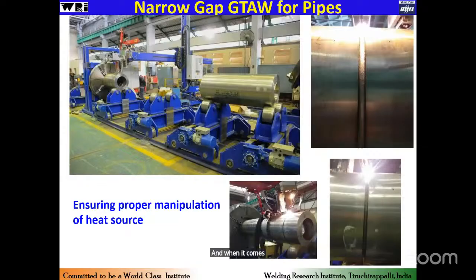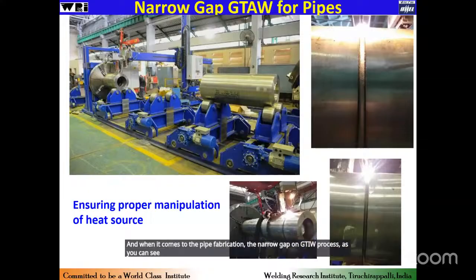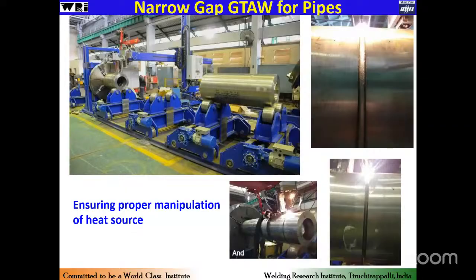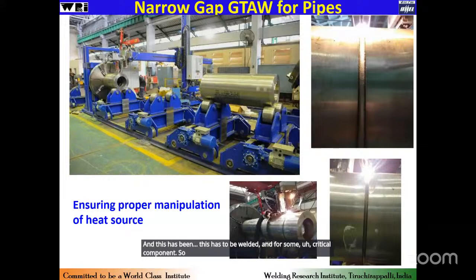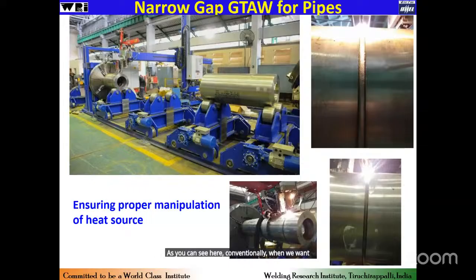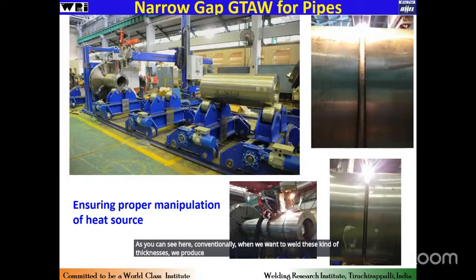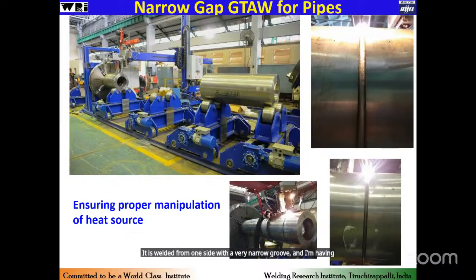And when it comes to pipe fabrication, the narrow gap hot wire GTAW process, as you can see here. Conventionally this grade of material is a nickel based superalloy, which has a thickness of more than 100 millimeters, and this has to be welded for some critical components. That necessitated the use of this advanced process called the hot wire narrow gap GTAW process. As you can see here, conventionally when we want to weld this kind of thickness, we prepare an edge with wider angles so that the torch is able to access the root. But in this case, it is welded from one side with a very narrow groove having an angle of 2 to 6 degrees at the top, and we were able to complete it with a single pass per layer.